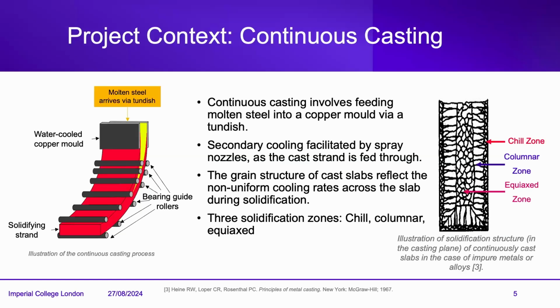A bit more about continuous casting. Essentially, you're taking molten steel and putting it into a water-cooled copper mold, which initiates the solidification process, and then this is extruded out as the solidification continues. It's guided through, and when the solidification is complete, it's cut to length. Due to the nature of continuous casting, you end up with an extremely anisotropic microstructure. On the outside, which cools the quickest, you have the chill zone with the smallest grain sizes that are randomly orientated. As you move further in, you encounter the columnar zone, which has textured grains that are aligned with the direction of heat flux. In the middle, you have equiaxed grains, which again are randomly orientated. Grain size wise, you have the smallest grains in the chill zone, the largest grains generally I've found are in the columnar zone, and in the middle, you have the equiaxed zone.